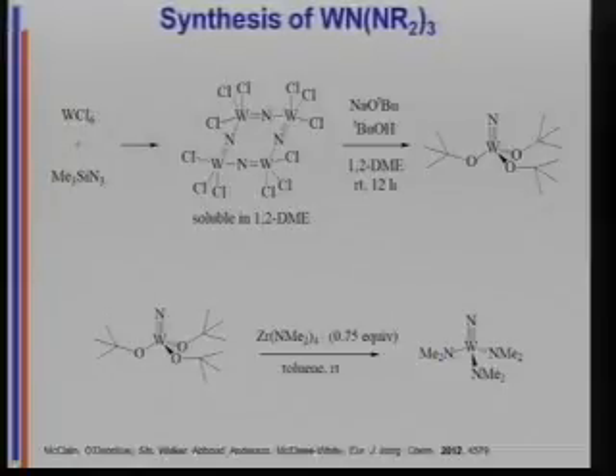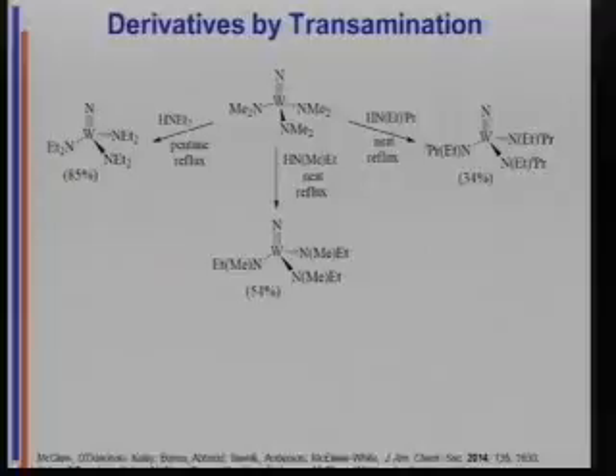The part that was brilliant on the part of my students was they figured out how to break up this tetramer with t-butoxide, which brings you to this compound, okay? And then we join the Cummins synthesis here and take that compound and transaminate, and that gives you this compound. And if you want more of these, you can continue the transamination process. Because dimethylamine is volatile, you take any other secondary amine, put it in there, you get transamination, blow off dimethylamine, and we can make all kinds of these.